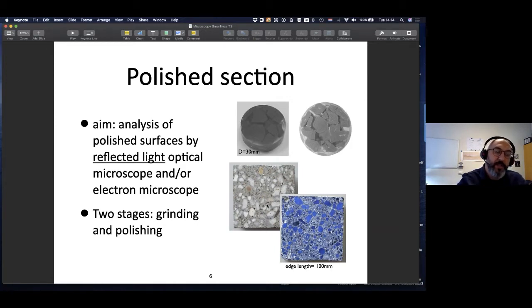So typically there are two stages you can think of if you want to prepare polished sections. These are called grinding and polishing, but actually they are the same thing. All we do is just scratching our material surface, finer, finer, and even finer. So fine that we will not be able to see those scratches even under the microscope. Then you call it polished. Actually, if you go super deep, then you will see those scratches at a submicron level. But that's of course something we're not interested in. All we want is a well-polished surface at the magnifications we're interested in.